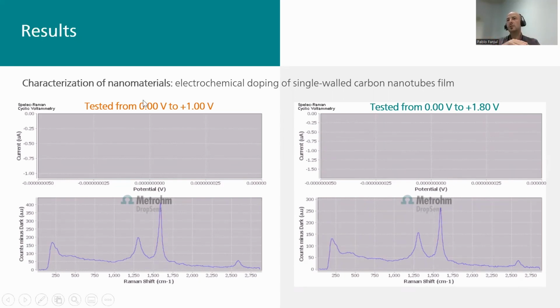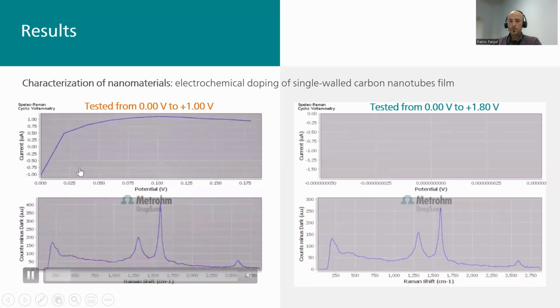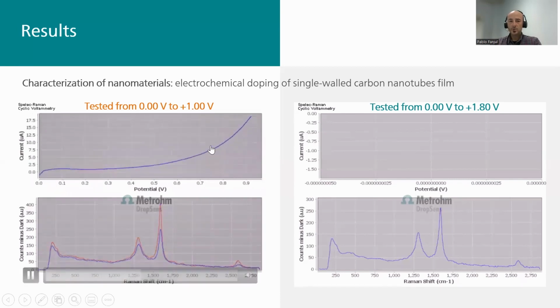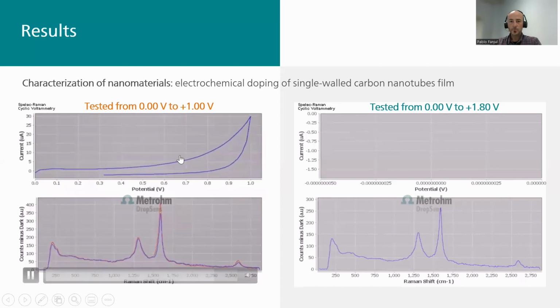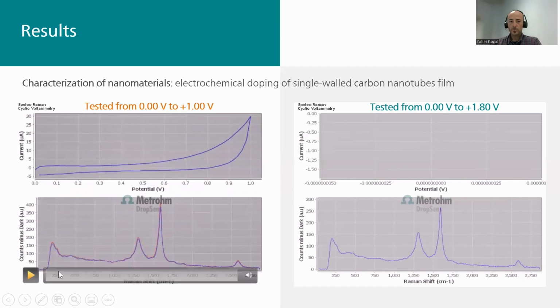So imagine that you have one of these electrodes completely covered with single wall carbon nanotubes. So we have the D and the G band of the carbon nanotubes. This first one is related to the defects of the carbon nanotubes, and this one is related to the sp2 configuration of the carbon material. And I will show you the evolution of this Raman spectra during a cyclic voltammetry going from 0 volts to +1 volt. This is done just in an electrolyte solution in potassium chloride. So I will show you it again.